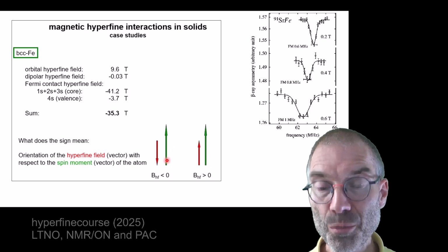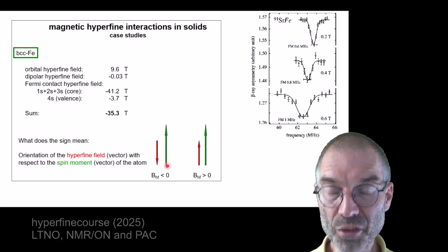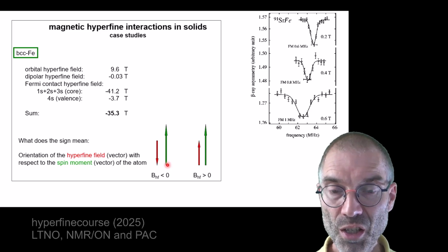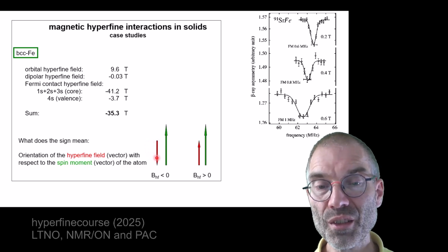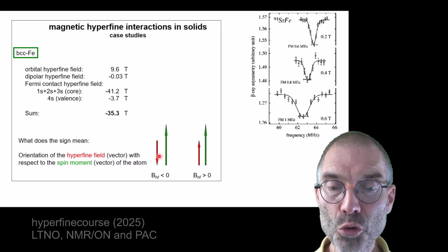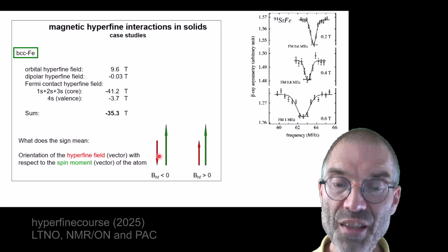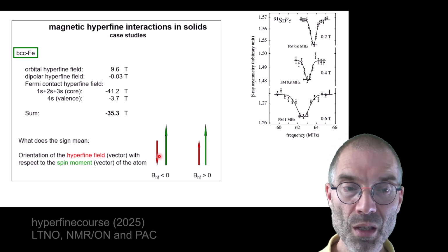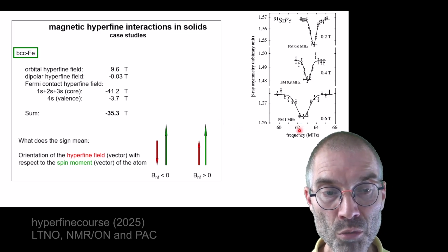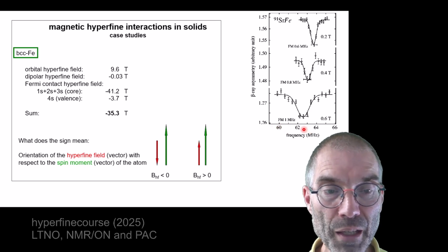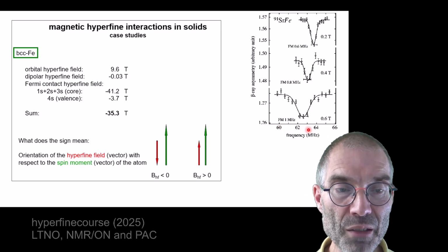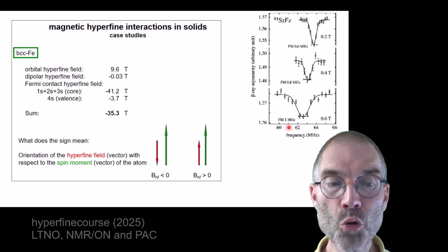And now that positive external field becomes a bit larger, so it cancels a bit more. We are left with a still negative total field, but a bit less in value than before. So indeed, our effective field, the effective splitting of the hyperfine levels, moves to lower values.